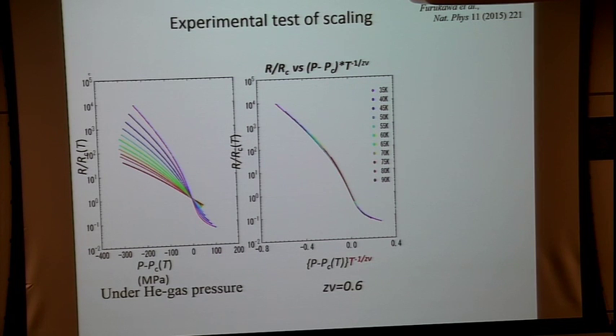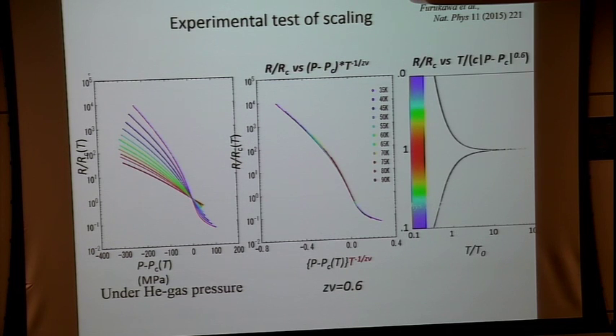This is a quantum critical scaling. Did you scale it with T or T minus Tc? No, T. No T minus Tc. Okay, so if you take T over T0, where T0 is the reduced temperature, this data collapses to two branches. This is experimental data, not calculation. All of the experimental data collapse to the two branches. This is an insulating branch. This is a metallic branch. And these universal curves have nearly perfect mirror reflections. And this is the very characteristic of quantum critical behavior.